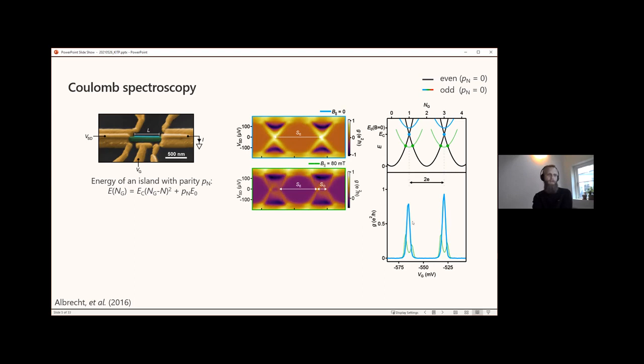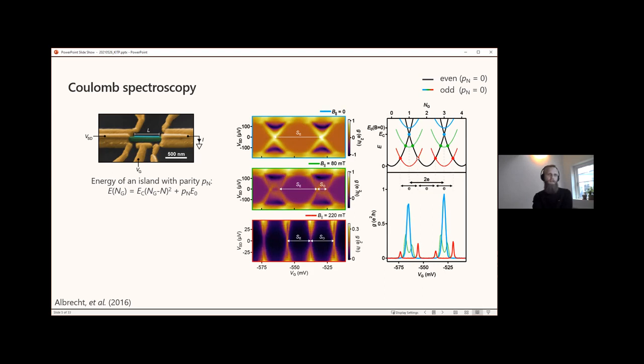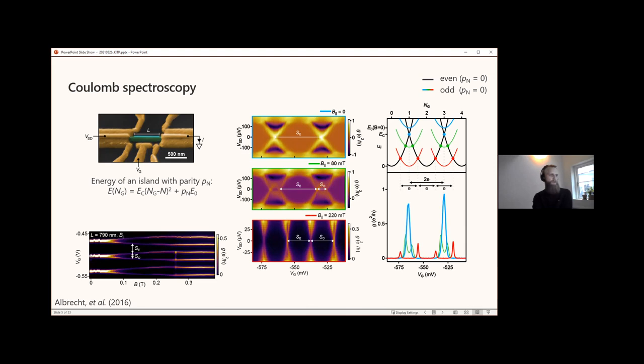Finally, if you keep increasing the magnetic field, the subgap state decreases to around zero energy, and then we end up having 1e periodic Coulomb blockade. If we take a cut at zero voltage bias and plot it as a function of magnetic field, we see how the Coulomb blockade peaks evolve from 2e periodicity to even-odd and eventually 1e periodicity.